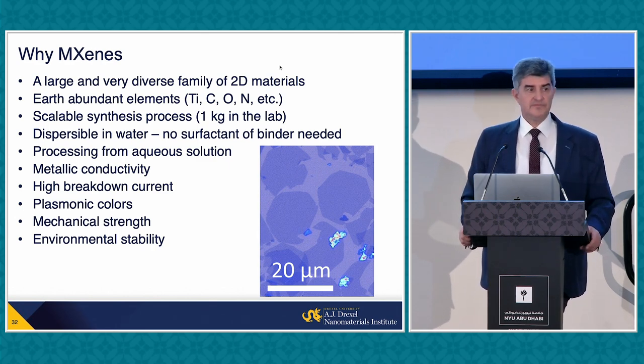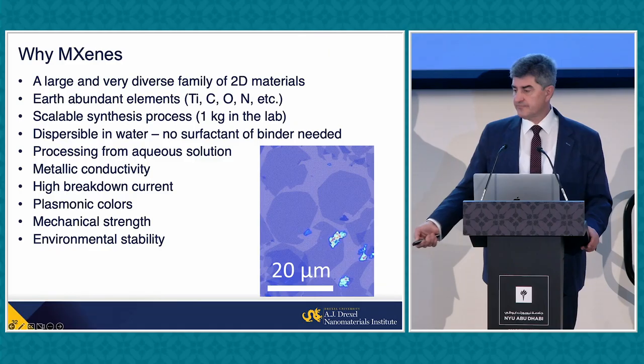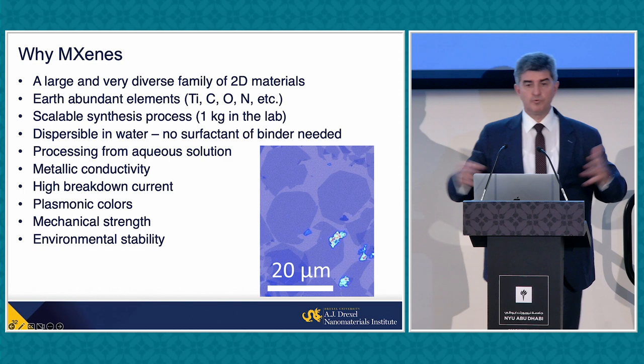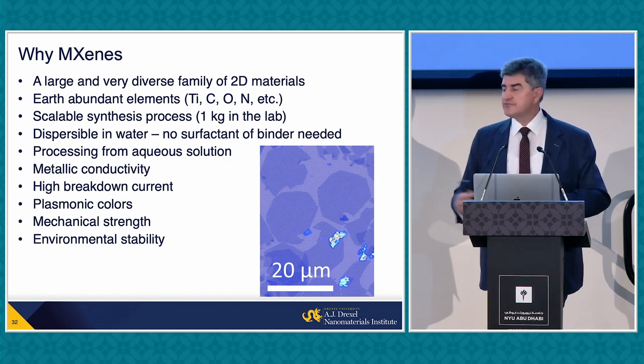Also, let me mention, there will be two papers coming in Science and Advanced Materials in the next couple of weeks. Our paper, and a paper by Dmitry Talapin, describe direct synthesis of MXene from two-dimensional oxide in our article, and from graphene, graphite, and by CVD in the article by Dmitry Talapin. So there are other methods emerging. And what you see here, for example, is about 20 micron flakes of MXene, single layer flakes. It's optical microscopy. You can see it on a silicon wafer with oxide here. And we're trying to push it to 40, 50 microns, so that we can make large flakes by solution processing.